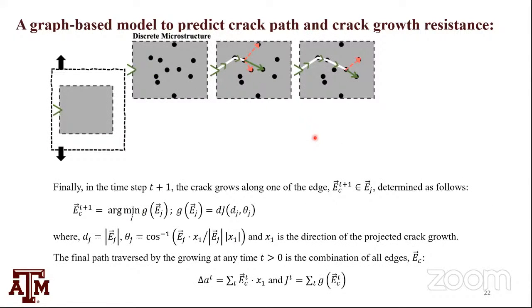All right, so now we need to know how the crack propagates. The crack propagation in this case, we'll define simply that the edge vector, out of the 3 vectors that I drew, or 4 or 5 that could be drawn within the limit of 2 times d inclusion, the crack chooses the vector at time t plus 1 which gives the minimum value of this function g.